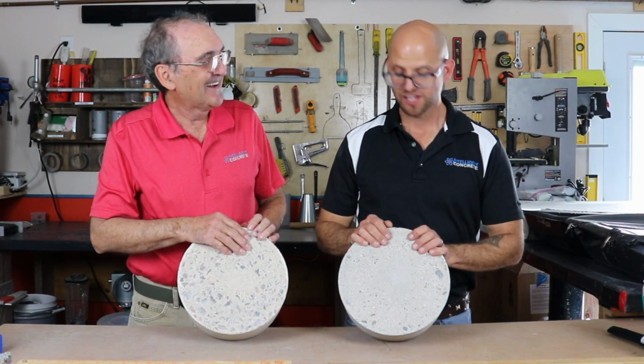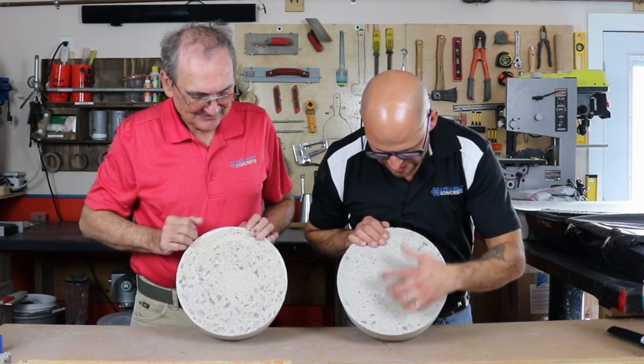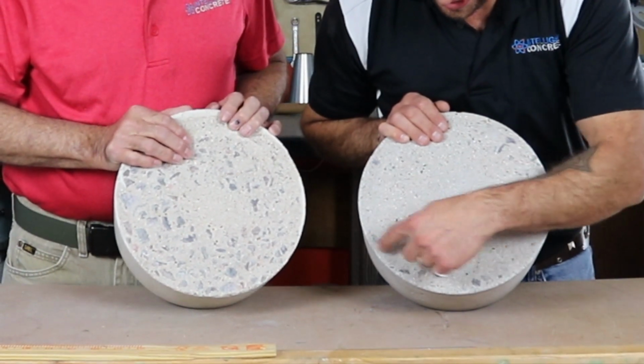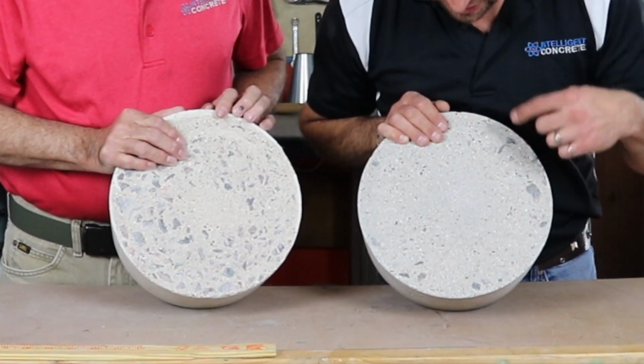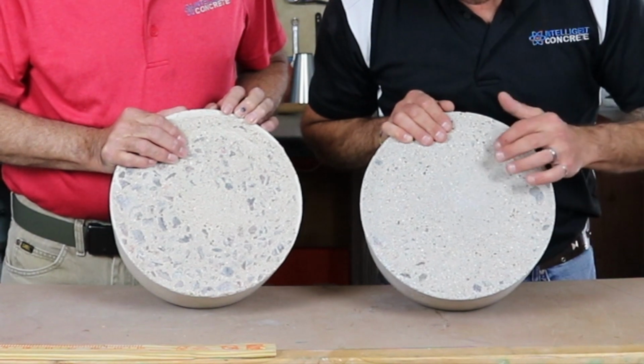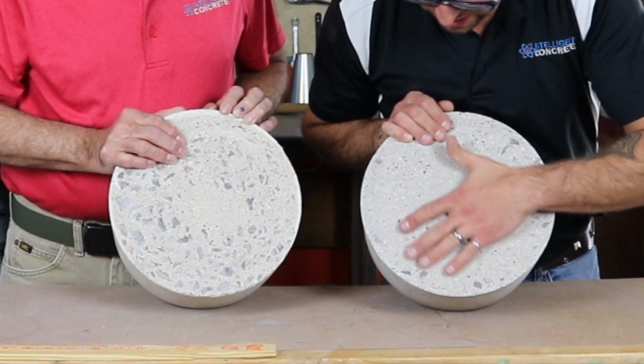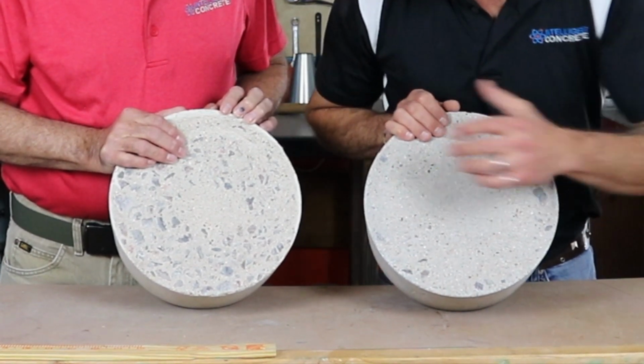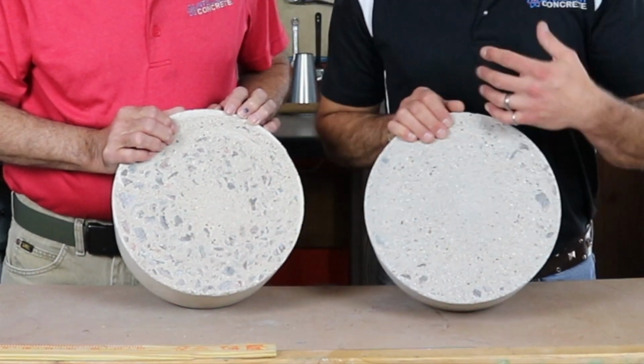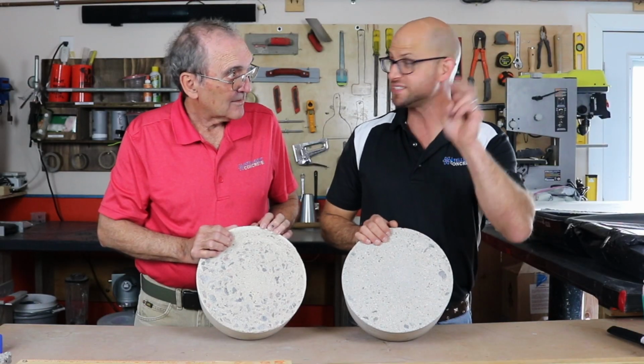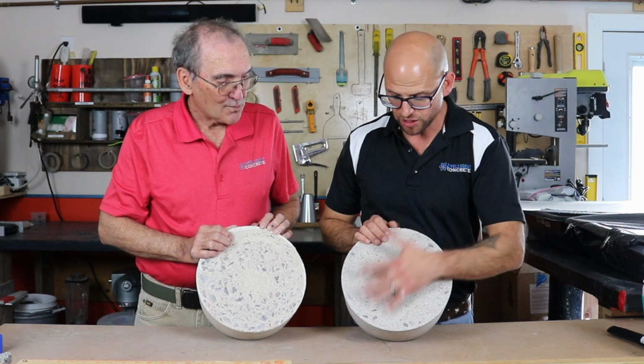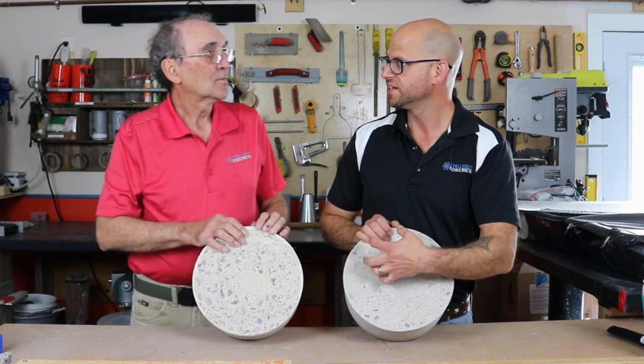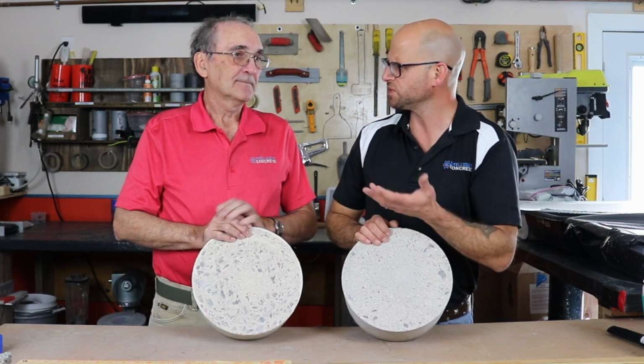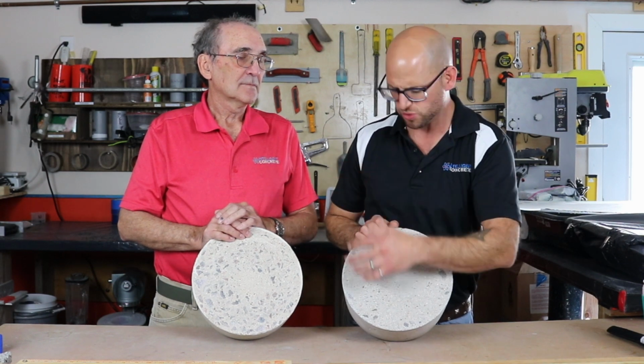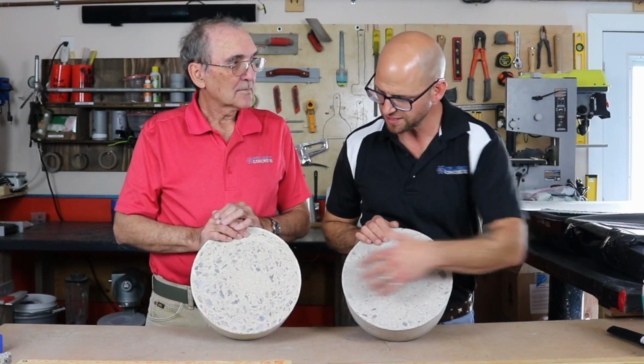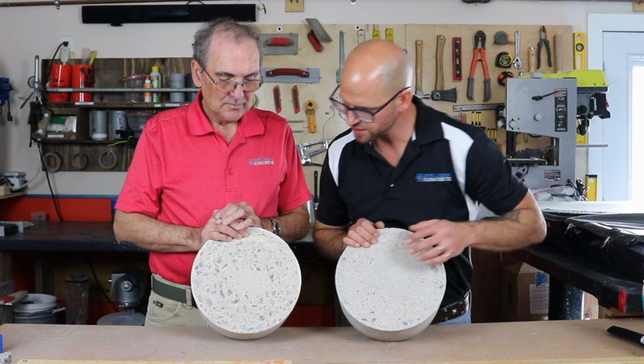It's so pretty. You can actually see the paste at the top surface. And yeah, you're starting to see some of the aggregate underneath that top sacrificial layer. But this is just absolutely gorgeous, where you're not seeing that exposed aggregate. So the steel balls, that simulation of erosion, the concrete was just too tough to allow it in that time limit, which I believe was 36 or 72 hours that we did, to tear away that top surface and expose that aggregate that was underneath.